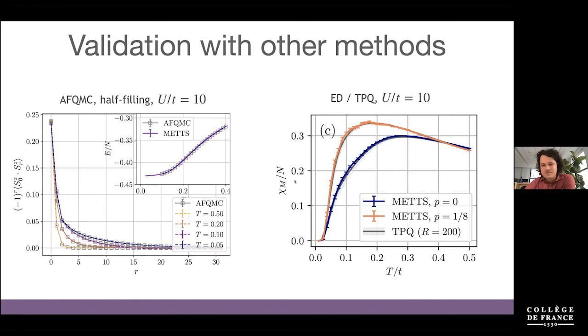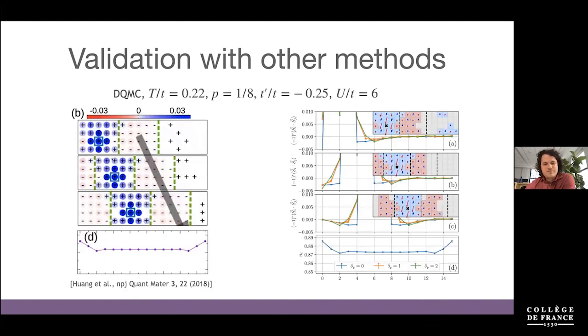And also here, what I'm showing is the magnetic susceptibility. We have also perfect agreement with this exact diagonalization results, an extension of one I call TPQ. So this is also valid, especially at the doped case, which is not captured by AFQMC. And finally, what we added recently is a validation with a very nice and interesting point where there have been these quantum Monte Carlo simulations at finite temperature, finite hole doping, and also at T prime at a slightly lower U.